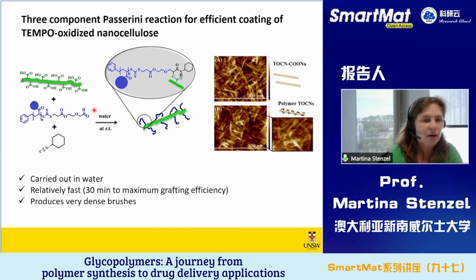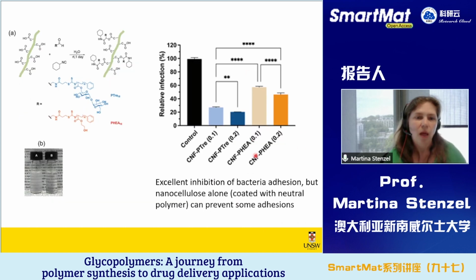So what we've done here is we made a trehalose polymer, and that trehalose polymer has an aldehyde functionality. That aldehyde functionality, together with an isocyanide, can very quickly coat nanocellulose with trehalose polymers. This reaction is called the Passerini reaction, and you can coat nanocellulose in less than half an hour. We have a very thick coating. You can see here that this coating process does not destroy your nanocellulose. So when we do that, we get trehalose-coated nanocellulose.